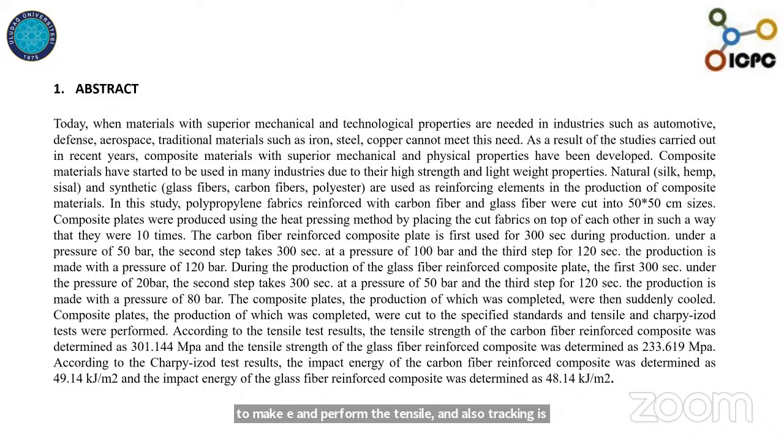According to the tensile results, the tensile strength of the carbon fiber reinforced composite was determined to be 301.144 megapascal, and the tensile strength of the glass fiber reinforced composite was determined to be 233.619 megapascal. According to the impact test results, the impact energy of the carbon fiber reinforced sample was measured as 49.14 kilojoules per square meter, and the impact energy of the glass fiber reinforced sample was about 48.14.